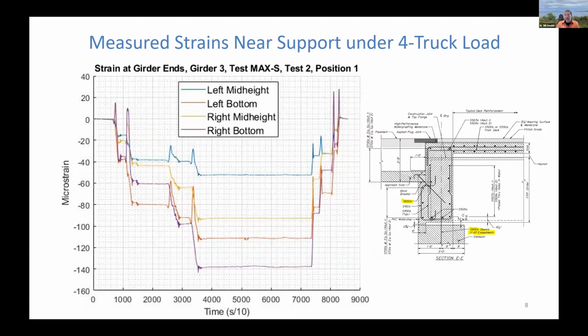It's a simple span. Why would we get negative moments? Well, the drawing on the right shows why we likely saw those. We have a heavy integral concrete diaphragm that runs the full width of the superstructure, rebar threaded through holes in every girder. And we can see that that also supports, via a little shelf, the concrete approach slab, which is doweled to that diaphragm. So that is going to tend to partially restrain the ends of the girder against rotation. That certainly could induce some negative bending. Not something we'd account for in design, not something we can really quantify, but it's definitely there.